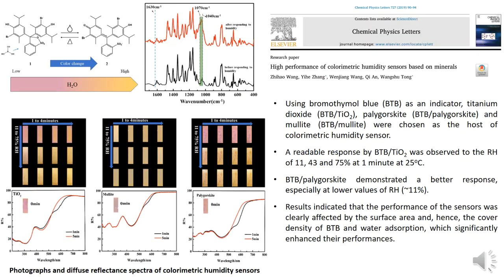This example is from a paper titled High Performance of Colorimetric Humidity Sensors Based on Minerals. In this study, the authors used bromothymol blue as an indicator for humidity, and titanium dioxide, palygorskite, and mullite were chosen as the host of the colorimetric humidity sensor. There was a readable response by BTB-titanium dioxide that was observed at RH of 11, 43, and 75% at 1 minute at 25 degrees Celsius. The BTB-palygorskite demonstrated a better response, especially at lower values of relative humidity around 11%.